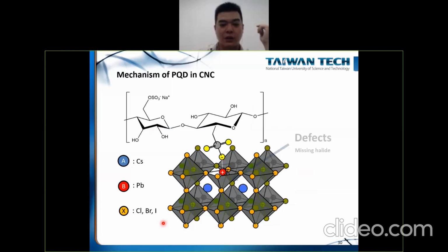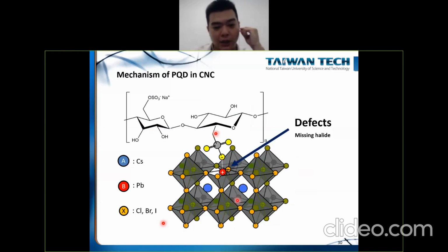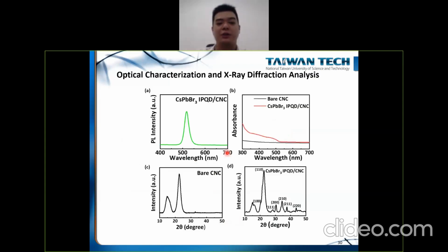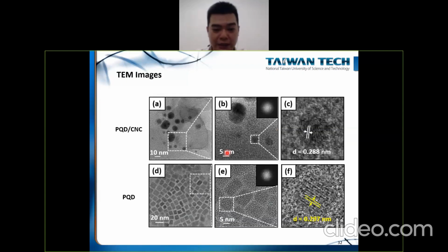So the underlying mechanism is that the sulfate functional group can be used to replace these missing halide defects in the perovskite quantum dots. Actually, this is a long chain structure for the CNC. Unlike traditional ligands, the quantum dots inside the CNC look like this.